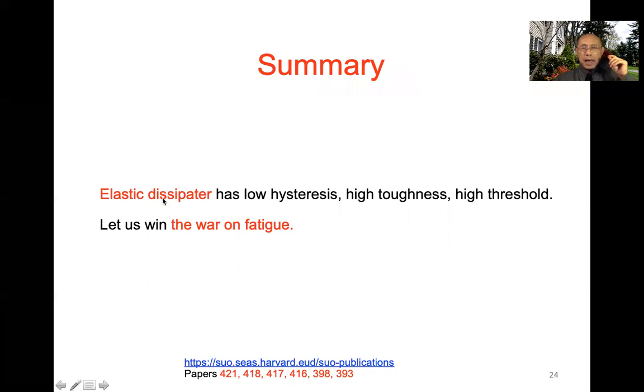So this idea, elastic dissipator, started with an elementary picture of Lake Thomas, that an individual polymer chain can release the entire energy of a chain. It's an elastic dissipator. You don't need to dissipate energy through plasticity. The consequence of this elastic dissipator is you have low hysteresis, which is very good for many applications, and you can have a high toughness and also a high fatigue threshold. I think now we have a handle to win this war on fatigue.